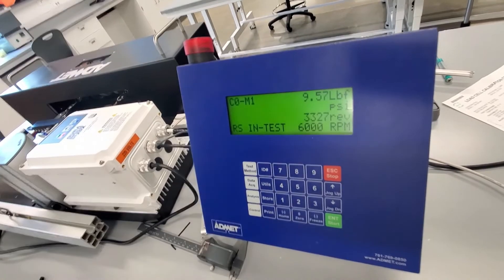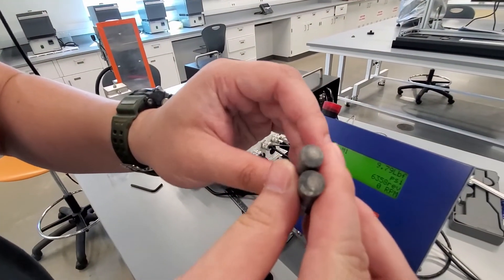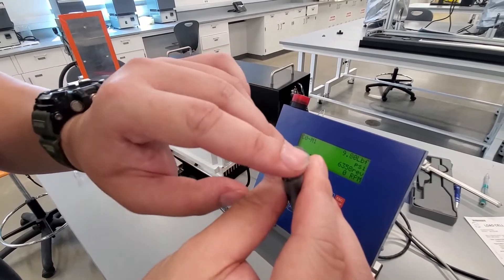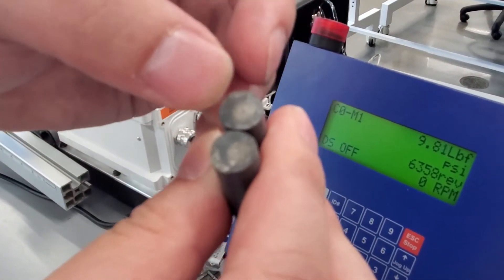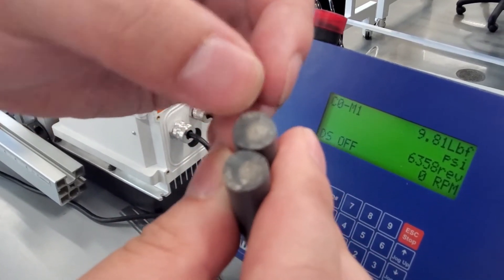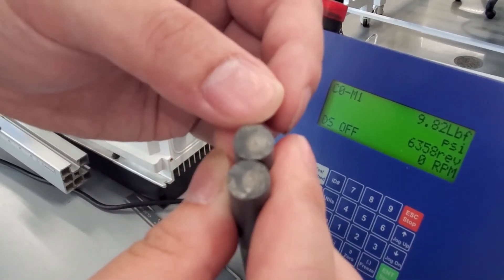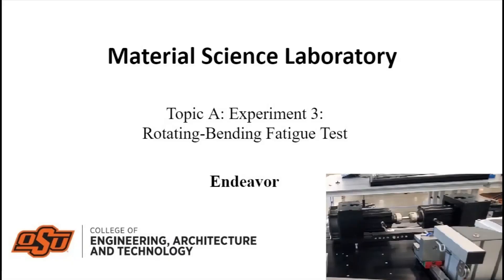So that's it. So once you fail, you can see the identical mark of the fractured surface of fatigue. On that surface, some portion of surface is pretty smooth and that's failure by propagation of the fatigue damage. And you can see some region where there are rough surfaces that is broken by the brittle failure. Okay, good luck students, have fun.